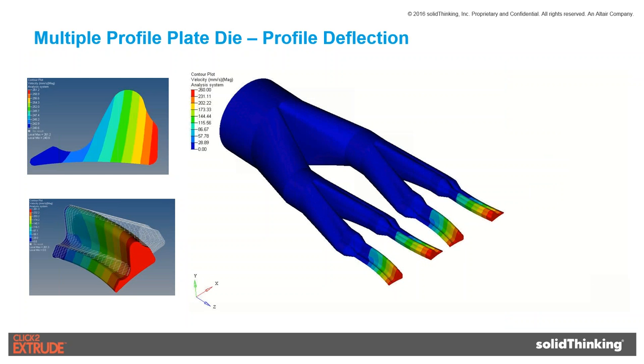Here I'm showing a die with multiple profiles coming out. The aim is to get a uniform profile in all the outputs. You may have designed the die geometrically symmetric, but due to the temperature gradient, the center could come out faster compared to the outer one, or vice versa. With Click2Extrude, we can understand, if multiple profiles are coming out, how each profile is coming out, and whether they are coming out uniformly. Here we can see, since there is a large variation in thickness, the thick section is coming out faster, and that is why it is twisting in one direction.